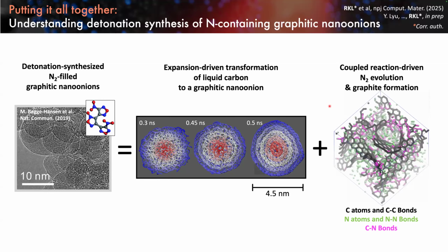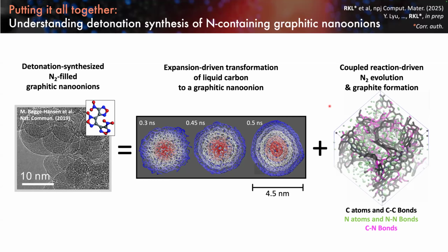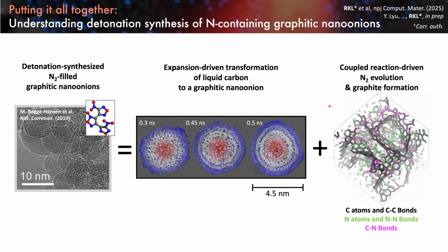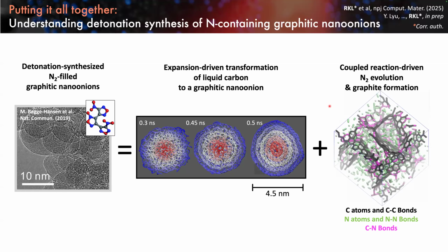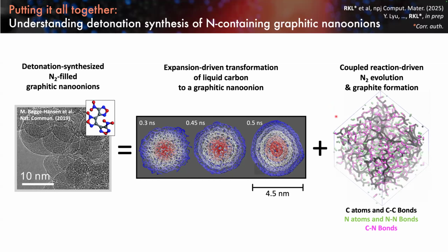It wasn't until we dropped well below where the carbon phase boundary, the melt line, would be, that you started to see phase separation. And it happened as this coupled reaction-driven event - we evolve molecular nitrogen out of our carbon-nitrogen bonds at the same time that we start forming these graphitic sheets.